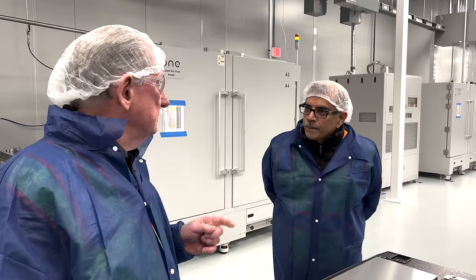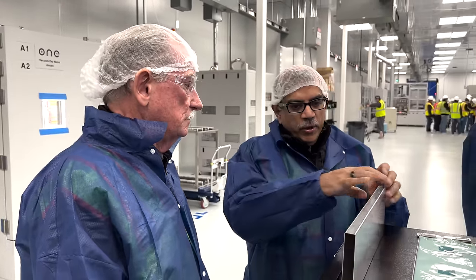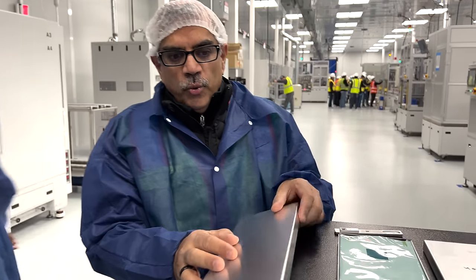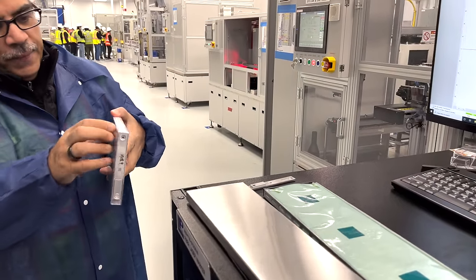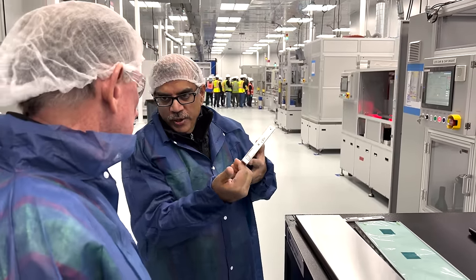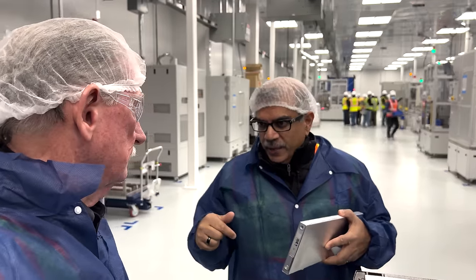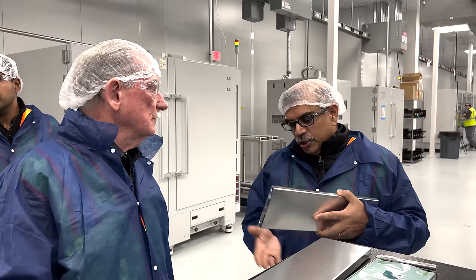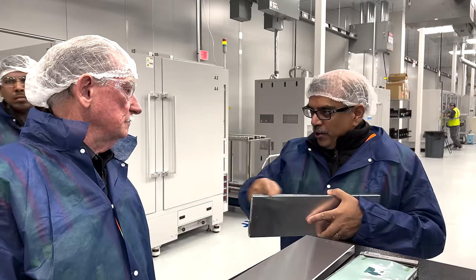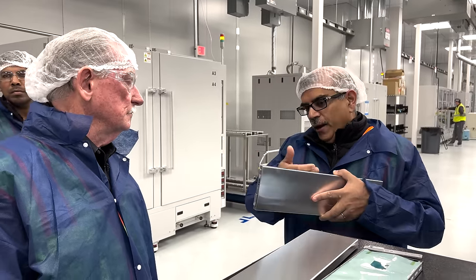The other thing is cooling — wicking away the heat. If you think about a pouch cell in the typical soft type, they put a heat sink on the cell. The metal can is a perfect heat sink by itself. What we do is mount the cells onto a cold plate — in the battery pack, the sidewall brings the heat down and we cool that surface. If you want fast charging, we've done fast charging with our LFP packs from 10 to 80% in 12 minutes. To do that, you have to cool the bottom and the top, so we put two cold plates, one on top and one on the bottom. If you want 20 minutes instead of 12, we can just use one cold plate and wick the heat down.